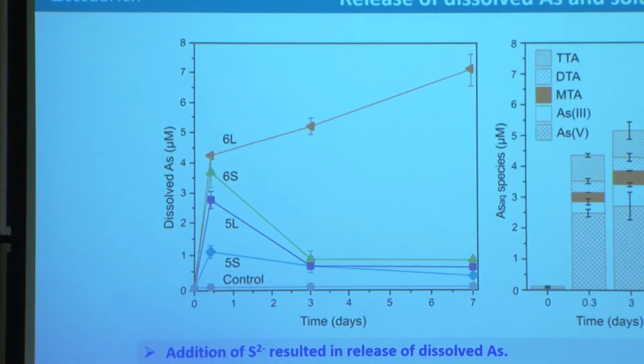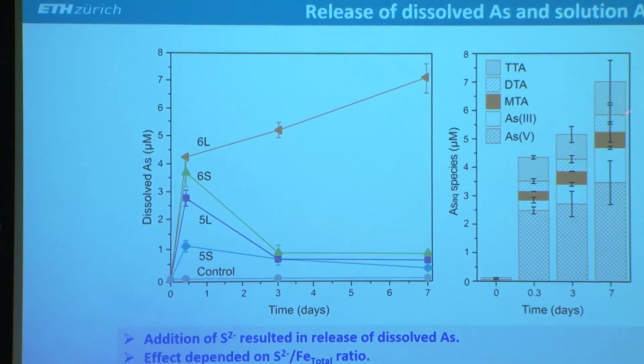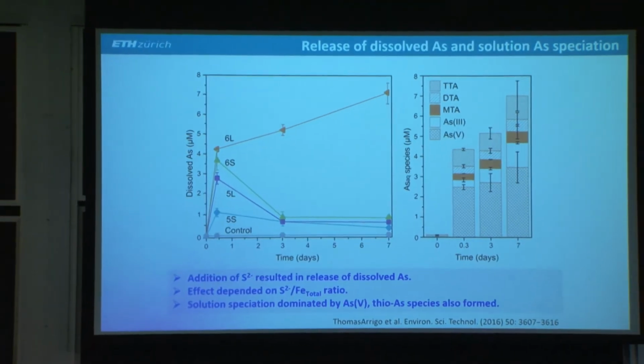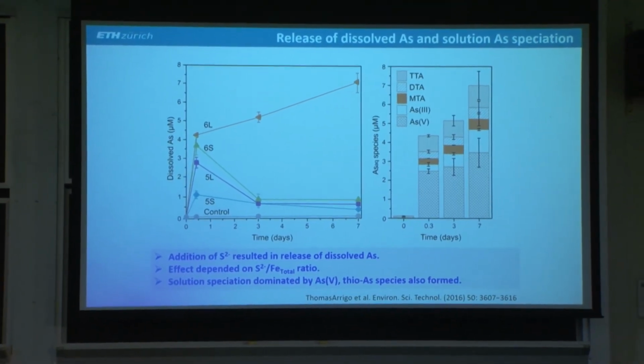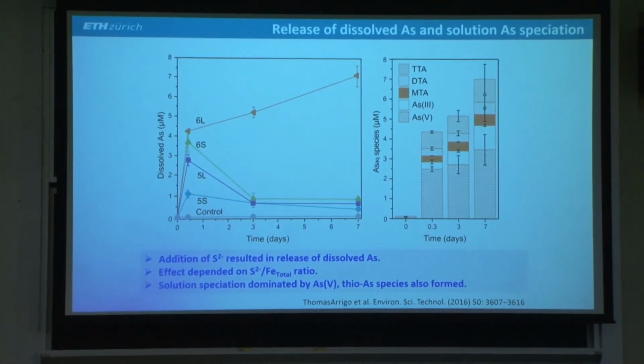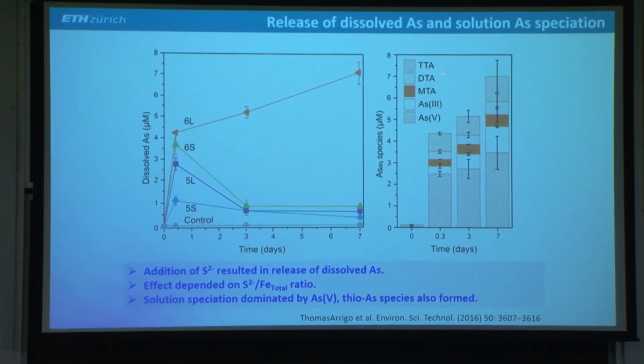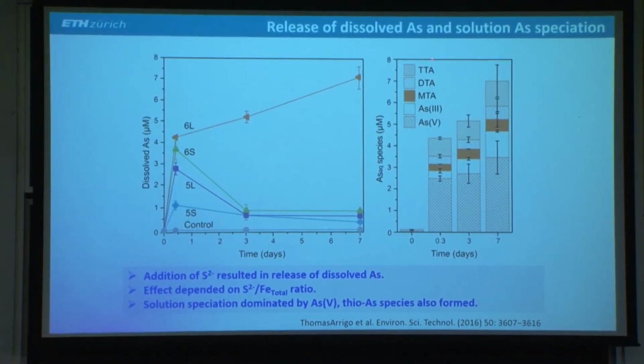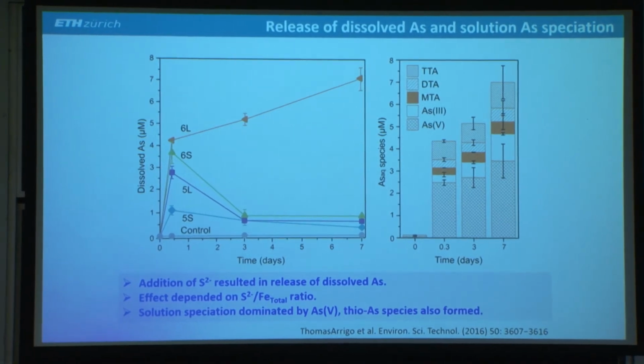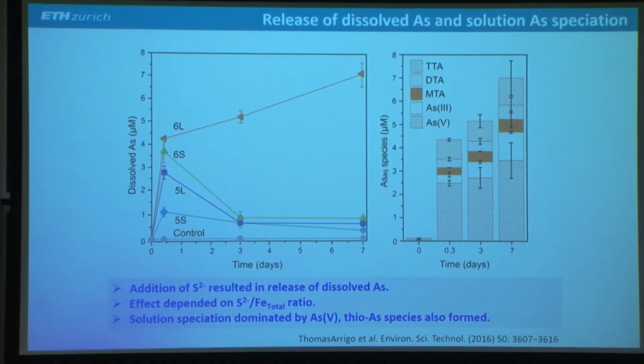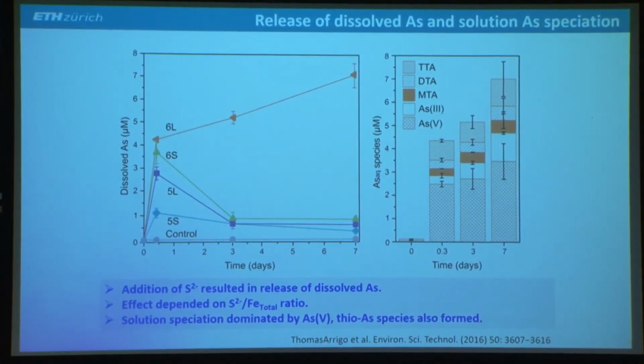And here we found that in solution, a very significant fraction of the dissolved arsenic was present as thioarsenate species. This is monothioarsenate, dithioarsenate, and trithioarsenate. And these species are known to form in sulfur-rich systems, for example, hydrothermal systems or other sulfur-rich environments.